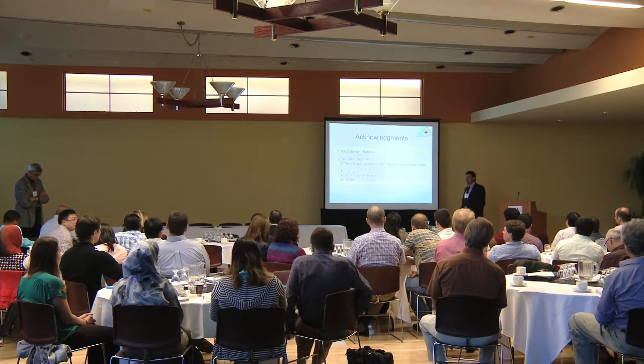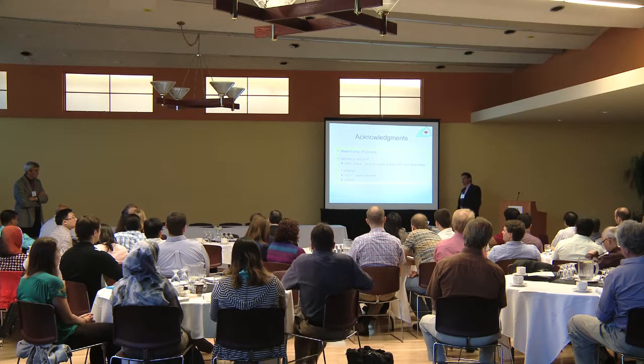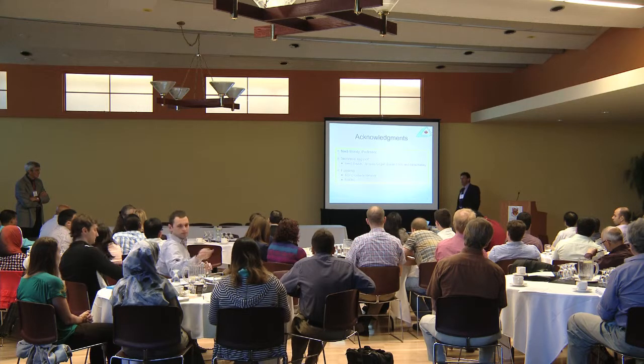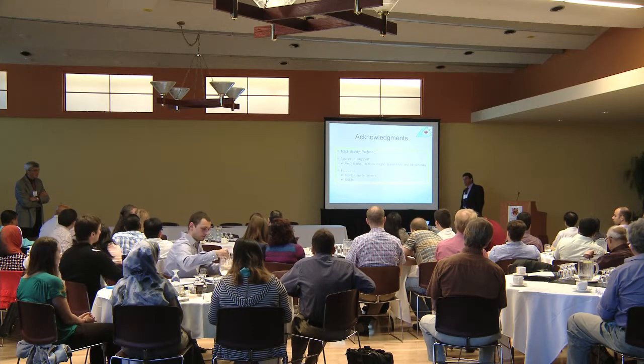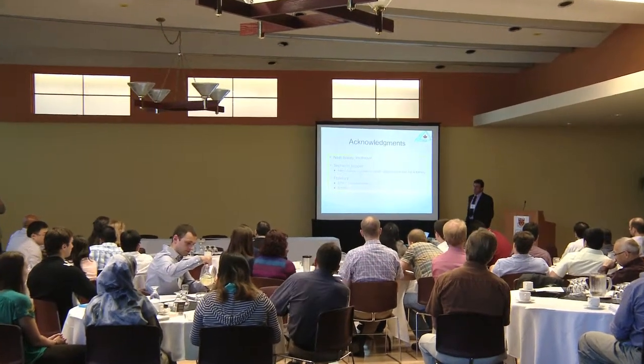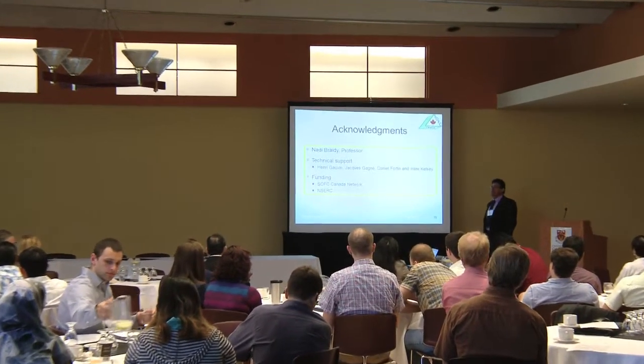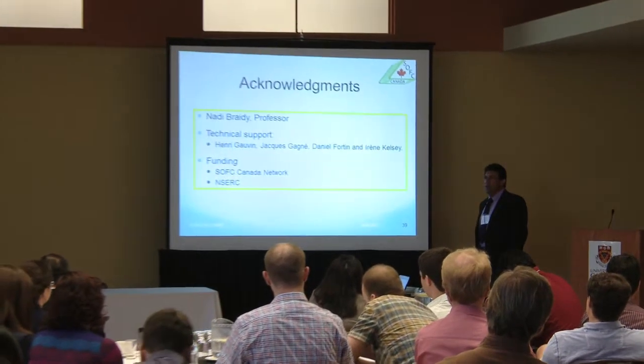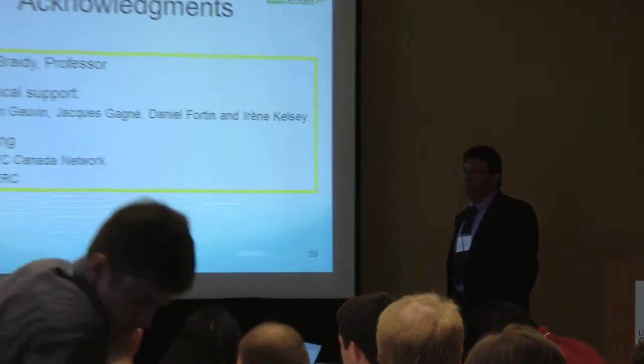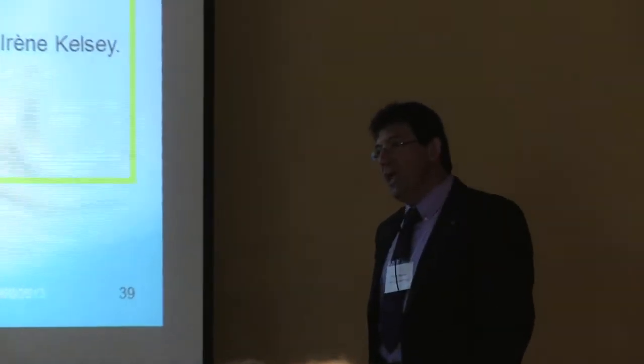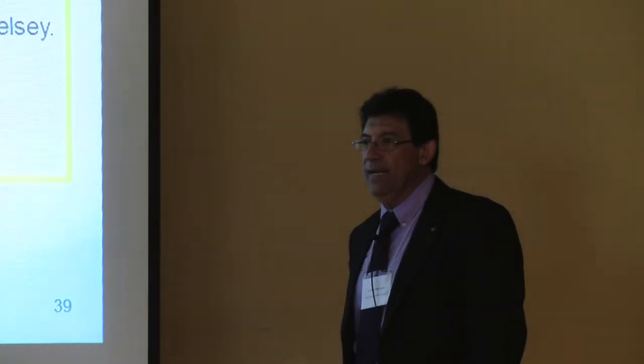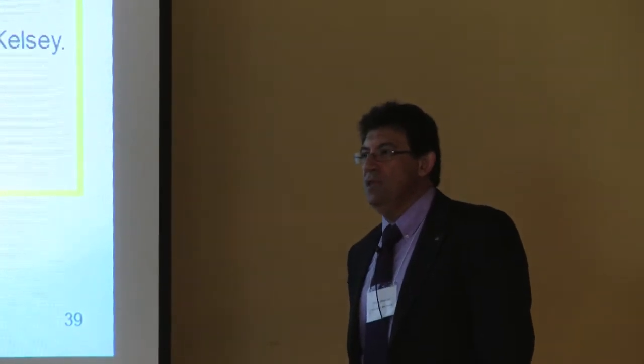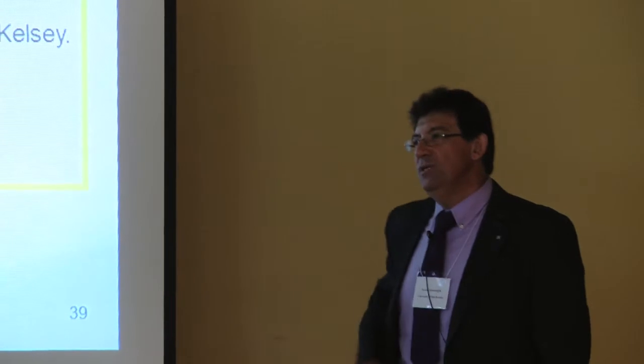And essentially in the next steps of this work, which are within the new network, the biofuel net, I promise to do that with methane, and essentially, you know very well in Enerkem, because you are contributing in this, to test the gasification tail gas reforming. Gasification tail gas contains a lot of methane, about 60 to 70%, CO and some other light hydrocarbons, C2. And the purpose is to do the same thing up to 1,000 hours with the gasification tail gas. And I think that this is critical for eventually having the industry being interested.